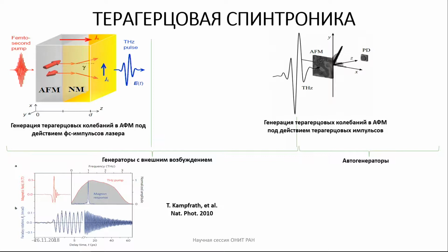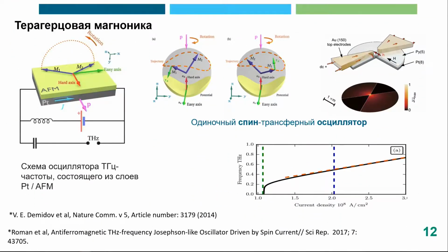So this, for example, is the case when you have two magnetizations and a small magnetic moment. You excite an electric current in platinum, and this permanent electric current, scattered by the surfaces of antiferromagnetic and normal materials, produces a spin current which goes perpendicular to the surface of the antiferromagnetic material. Spin current is a current of magnetic moment,